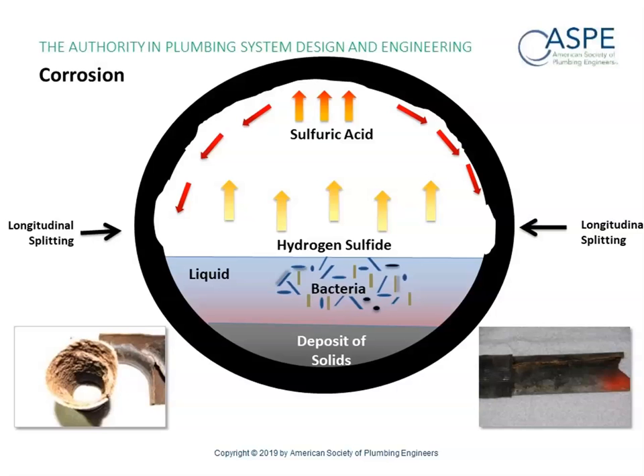Anyway, that hydrogen sulfide, being lighter than air, rises to the top of the piping system, and it condenses and forms sulfuric acid. That sulfuric acid then coats the inside of the pipe, hits the top level of the liquid or water or whatever's in there, but having a very low specific gravity, it sits on top. And if you don't have adequate flow, you end up with a longitudinal splitting in your piping system because that sulfuric acid is eating away at the interior of your pipe. Go ahead and advance, Jim.